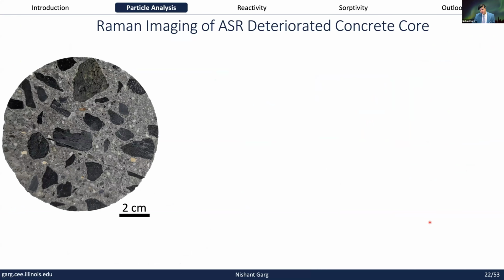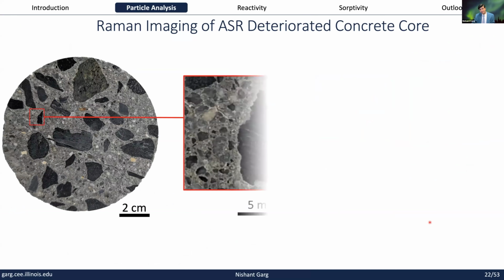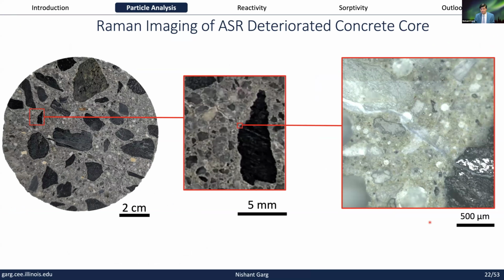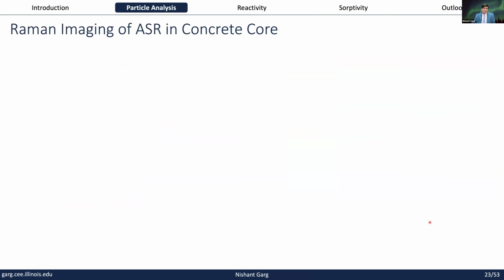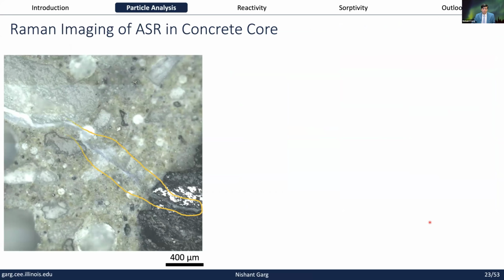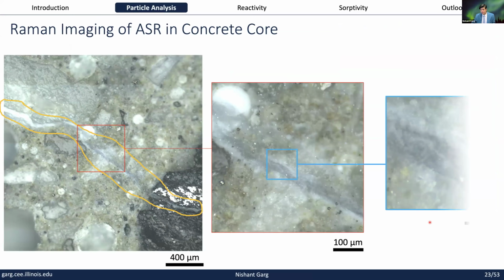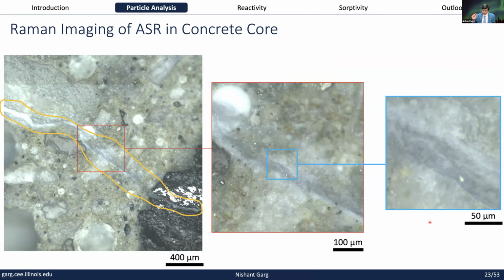Finally, for Raman imaging, one of the things we have also been doing in the particle analysis is looking at ASR. So these are some samples we recently obtained. We were interested in looking at where that ASR gel is, and if we can identify it. So if you look from left to right, we're zooming into specific regions here. And one of the things we really wanted to do was follow this kind of thin river of the ASR gel that is flowing in the aggregate. And you can see it's really 50 microns thin, and we wanted to see if we can map this